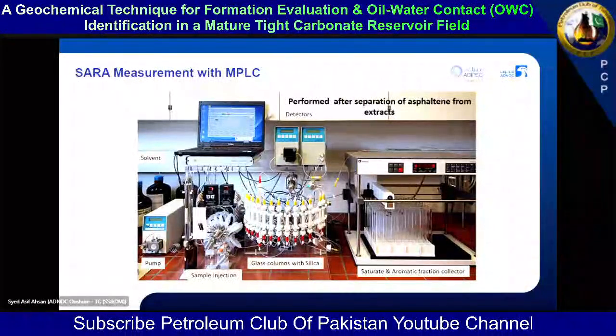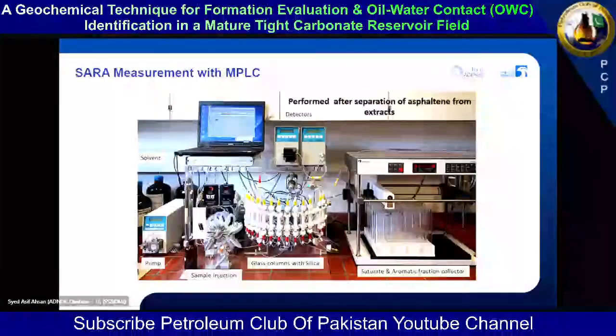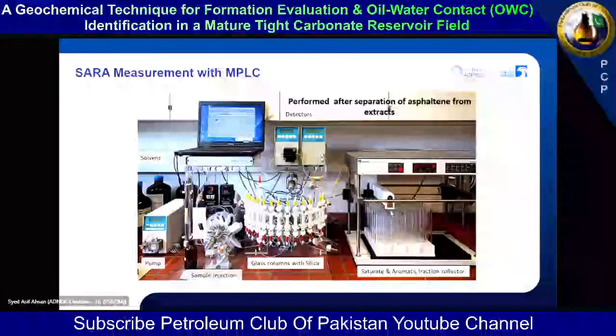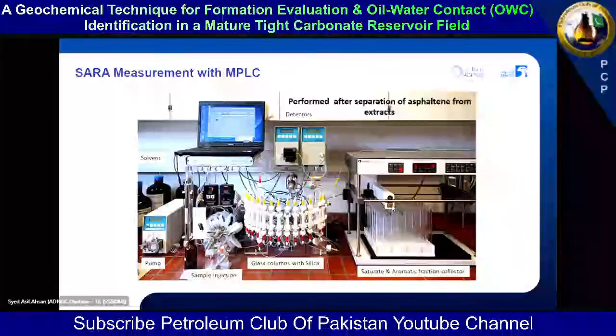And once this process is completed, the pump now starts pumping another solvent in a reflux cycle, and then it starts eluting aromatics with the other solvent, and that gets collected in the other glass container here. So basically, you have two components, saturates and aromatics, of the same sample collected in these two containers. With the solvent, of course.